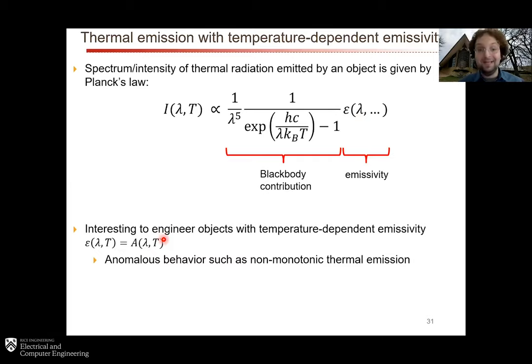So it's quite interesting to think about engineering objects with temperature-dependent emissivity, where that temperature-dependent emissivity changes fast enough with temperature to either counterbalance or even flip over this blackbody contribution, which has a fixed temperature dependence that you can never change. And so you can imagine that if this temperature dependence of the emissivity changes fast enough, you could have something like non-monotonic thermal emission, where you keep increasing the temperature, but the thermal emission doesn't always go up. It goes up and then down and up and down and so forth.